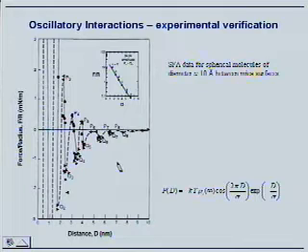They have taken a molecule, some siloxane, which has an exactly spherical molecule with a size of 10 angstroms, 1 nanometer. So you can imagine those small molecular balls between the surfaces, and then you start pressing them, and suddenly you start measuring when you go, let's say, below 10 molecular diameters. Now, 1 nanometer is exactly 1 diameter.